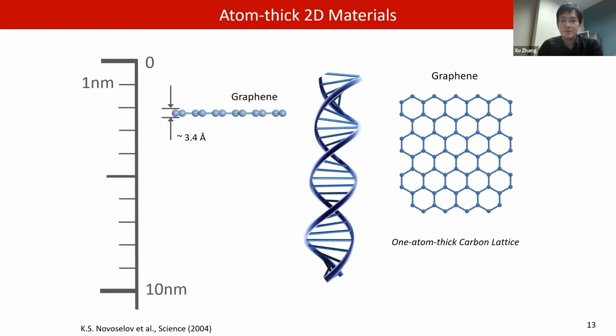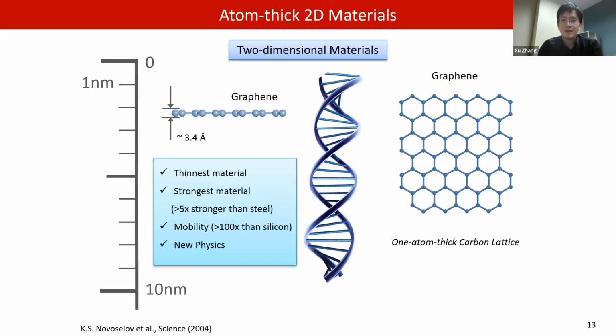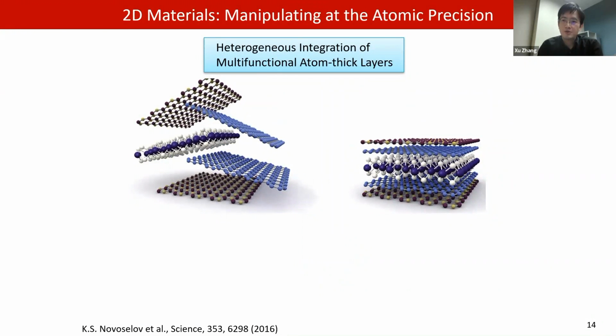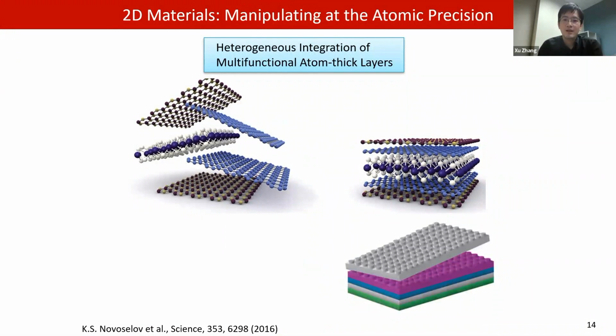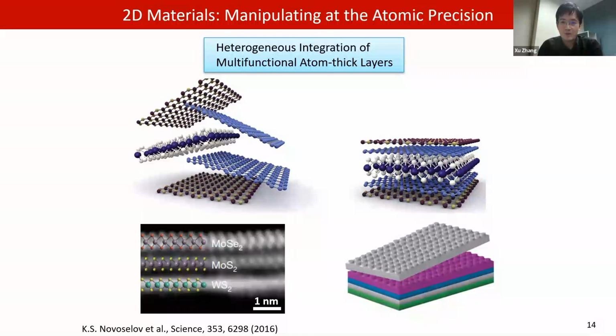With only one atom thick, its Young's modulus is 5 times higher than steel, mobility 100 times higher than silicon. Many new physics appear due to the quantum confinement in the z direction. A very unique property of 2D materials is that they do not have dangling bonds. It means that we can do straightforward heterogeneous integration of multifunctional layers. We can assemble these one atom thick materials in a layer by layer fashion. You can do it in whatever combination and order you want. It's just like building Lego squares. It is hard to think of any other materials that you can do it at the atomic precision and in a large scale and low cost manner.